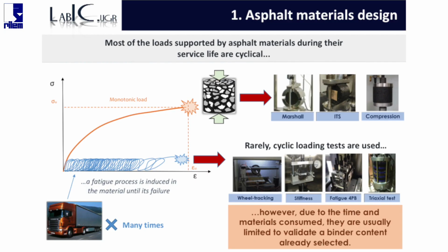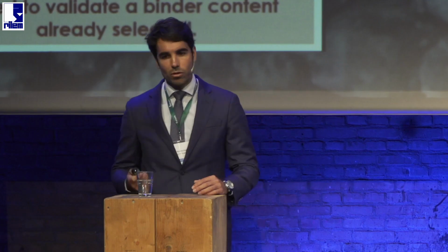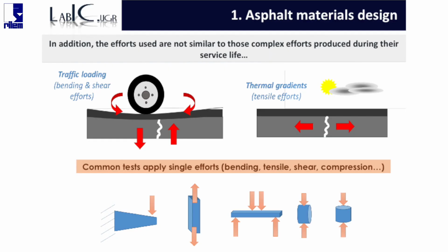Rarely, cyclic loading tests are used during the design stage, and due to the time and the material consumed on this type of test, they are usually limited to validate a binder content already selected with monotonic tests. In addition, most of the tests used when designing asphalt material do not apply similar complex effort to those supported by this material during their service life. Most of the tests apply single efforts such as bending, tensile, shear, but not a complex state like shear plus bending or plus tensile, as occurs in asphalt material.